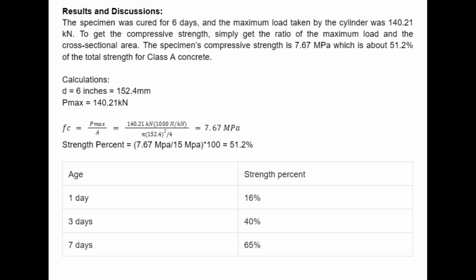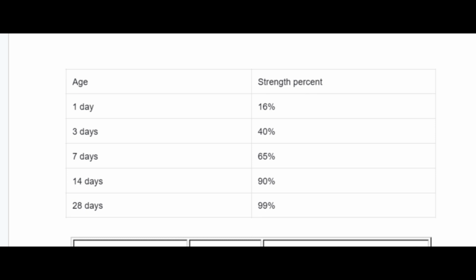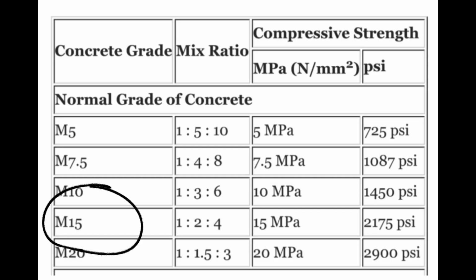The specimen's compressive strength is 7.67 megapascals, which is about 51.2% of the total strength for Class A concrete. The strength of concrete increases with age. The table above shows the strength of concrete at different ages in comparison with the strength at 28 days after casting. Now, Class A is M15 with 15 megapascal compressive strength at 28 days.